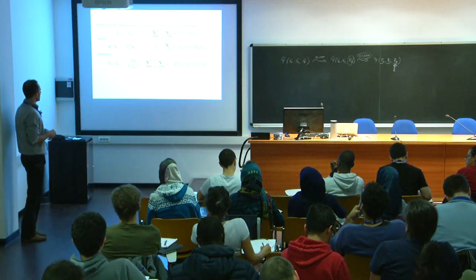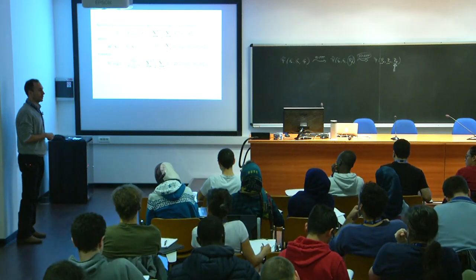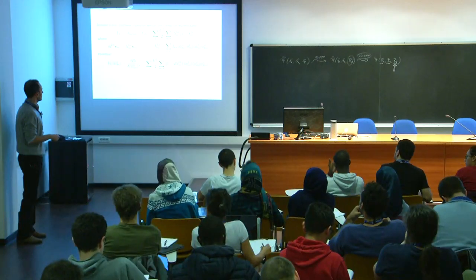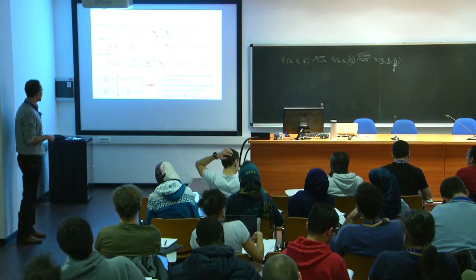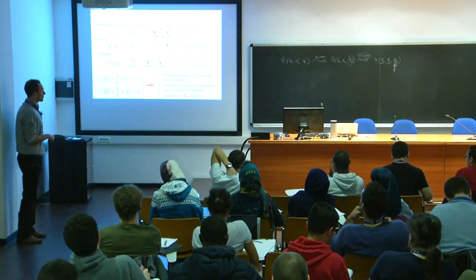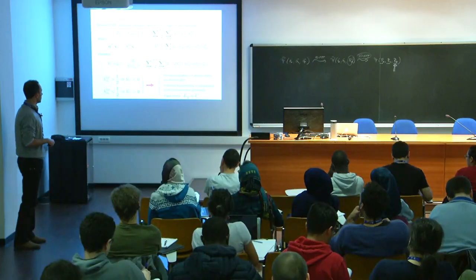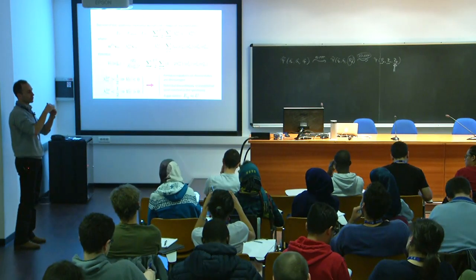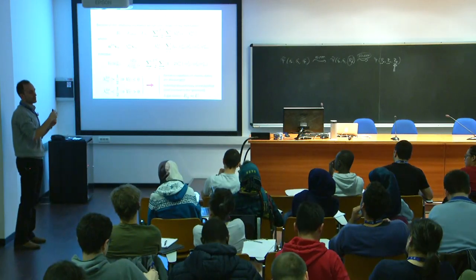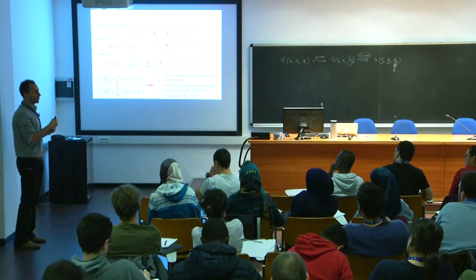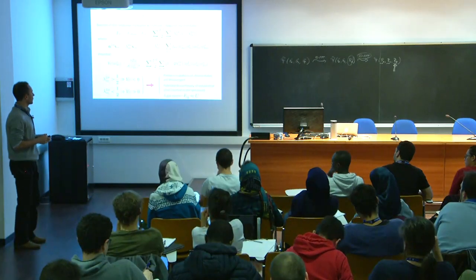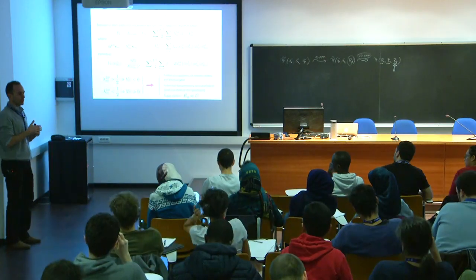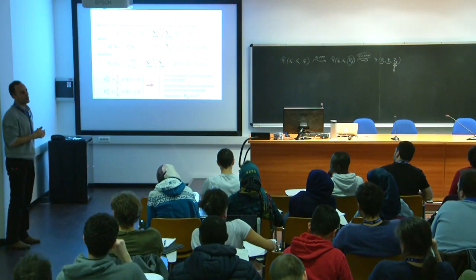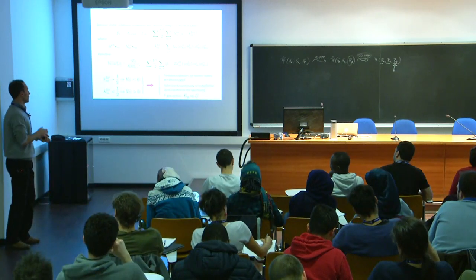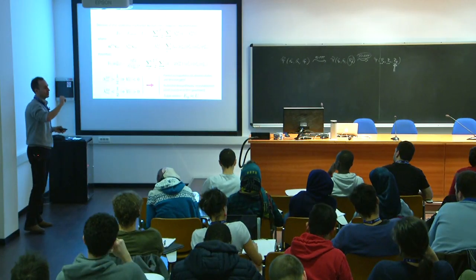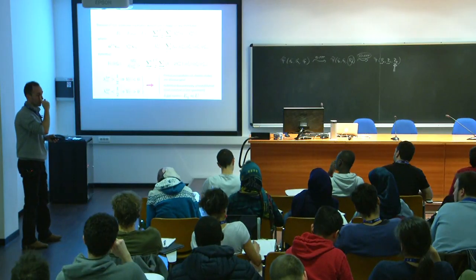So if you compute the potential, the pieces of the potential that go into the Koopmans equation, you get something like this. So you get a term that's attractive when you have more than half occupied states, and that's repulsive when you have less than half occupied states. So if a state is little occupied, try to empty that state. If instead it is more than half occupied, it tries to get the entire electron on there. That also opens a gap naturally in the Koopmans state, because it puts an energy difference between occupied and unoccupied states. That's how it works. That's why using this simple correction, you can expect the opening of some gap around the Fermi level.